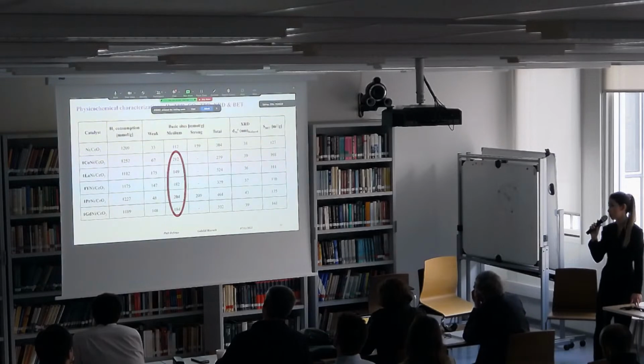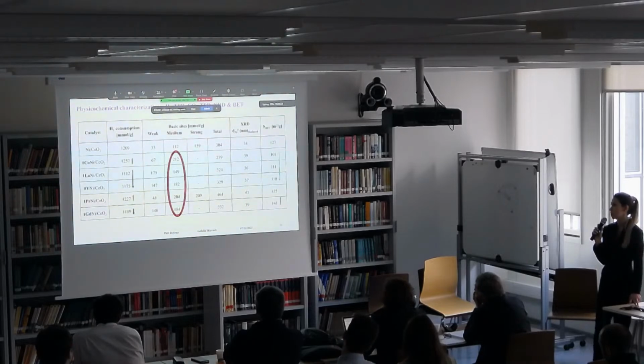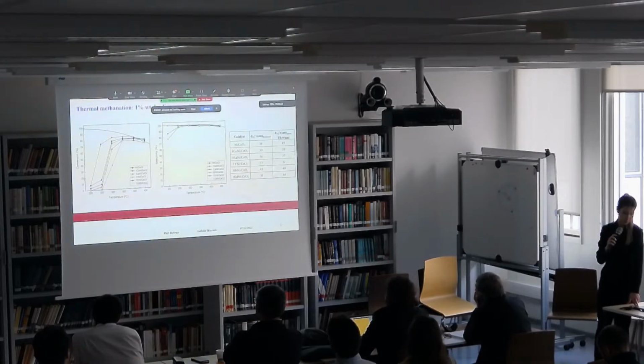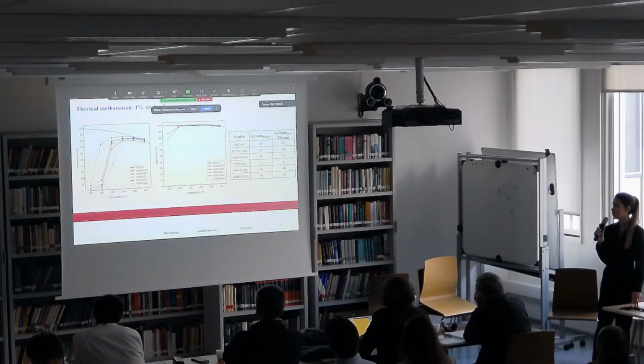Regarding the hydrogen consumption and also the BET surface area, it can also be seen that based on the type of promoter, different trends were seen. Also regarding the particle size, more or less all the samples have the same particle size. However, lanthanum has the smallest and the praseodymium promoted sample has the biggest particle size. Regarding the thermal methanation, the cobalt promoted sample showed the best catalytic performance as it has the highest amount of basic sites and hydrogen consumption.